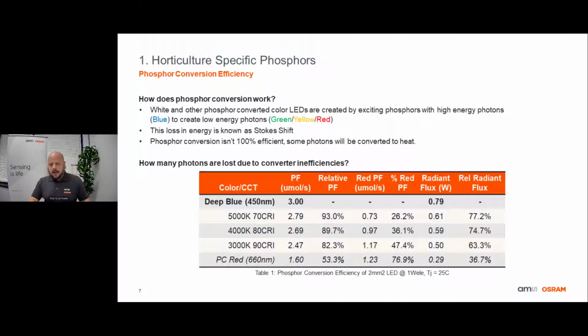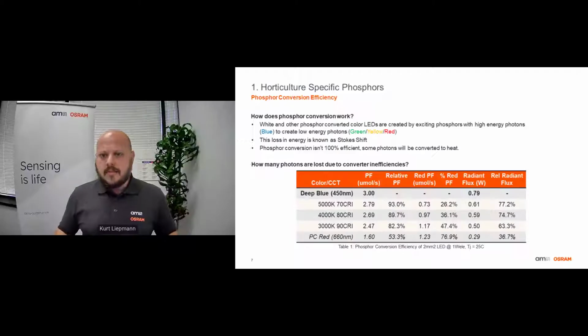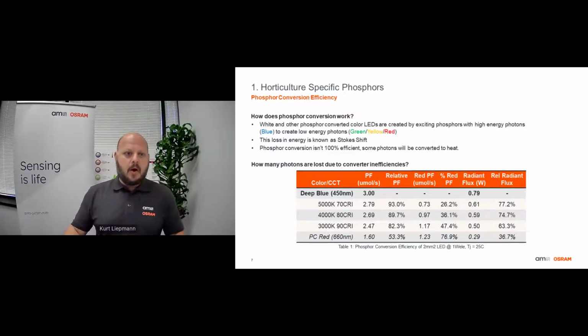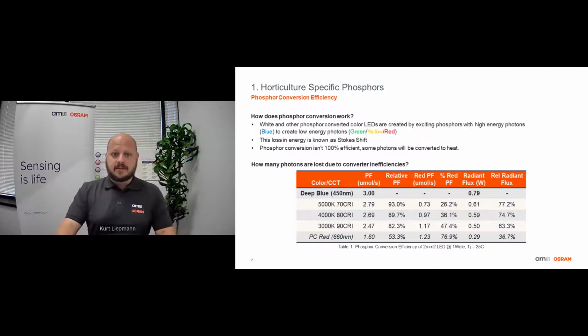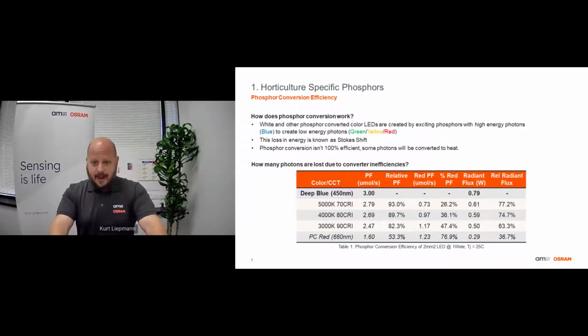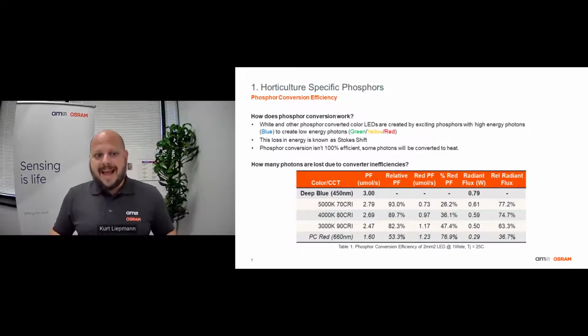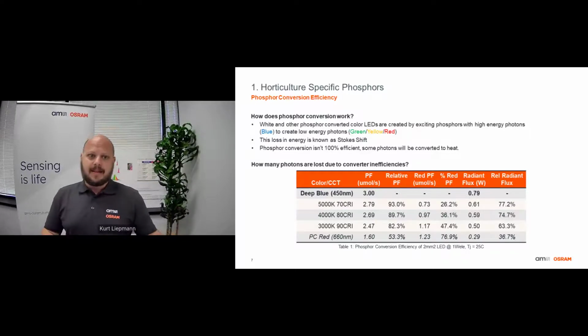As we progress to warmer CCTs with higher CRIs, we can see that the relative photon flux decreases as the percentage of red photons generated, specifically between 600 nanometers and 700 nanometers, increases. So the more red photons we are trying to create through down conversion, the less efficient the converter, and we are left with fewer emitted photons overall. This process actually is so inefficient that a phosphor converted red LED would emit barely more than half of the photons that it started with at the die level.